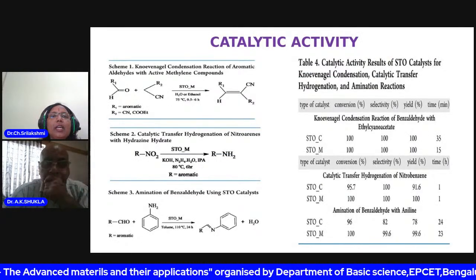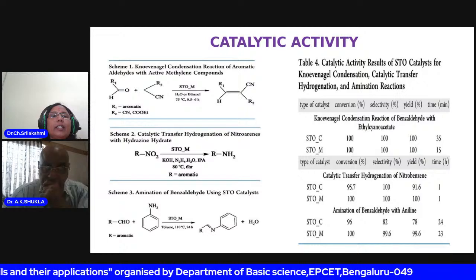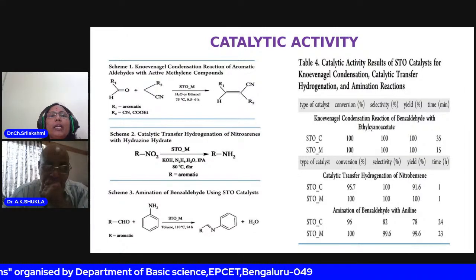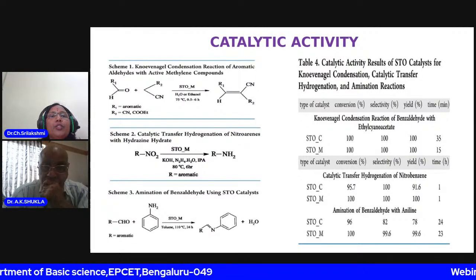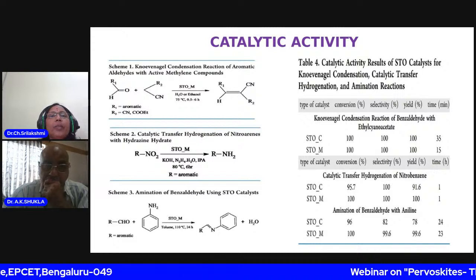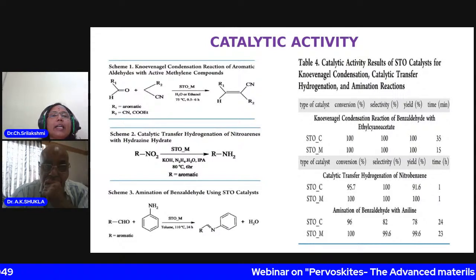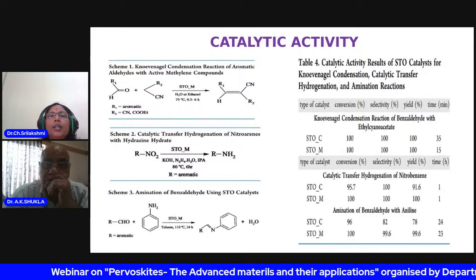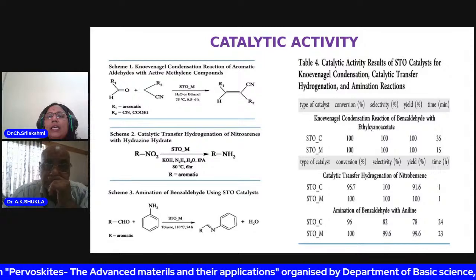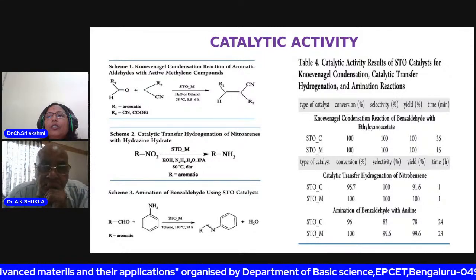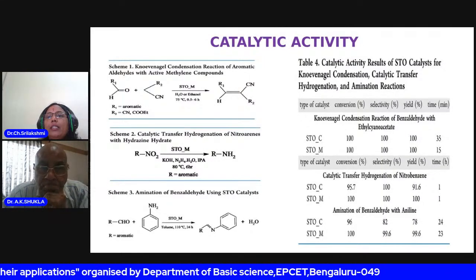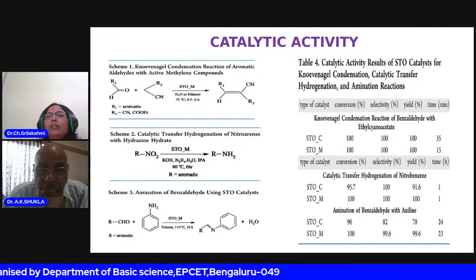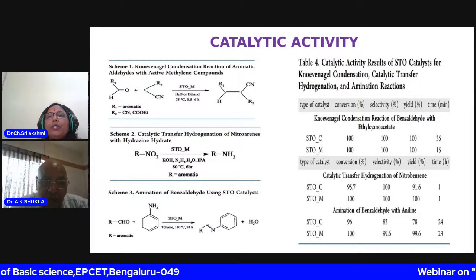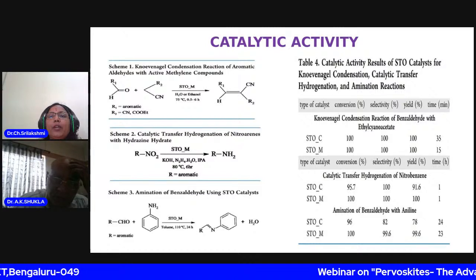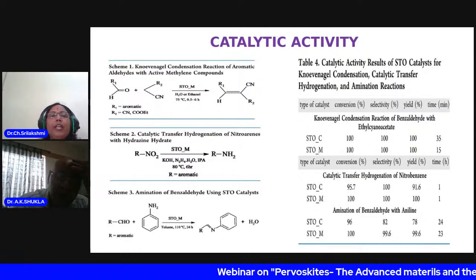And these are the reactions we have conducted. First is the Knoevenagel condensation, where benzaldehyde interacts with active methylene compounds, such as ethyl cyanoacetate, and you get alpha, beta-unsaturated compounds. Both catalysts showed good activity, but the conventional catalyst gave 100% conversion in 35 minutes, whereas the microwave material gave it in just 15 minutes.